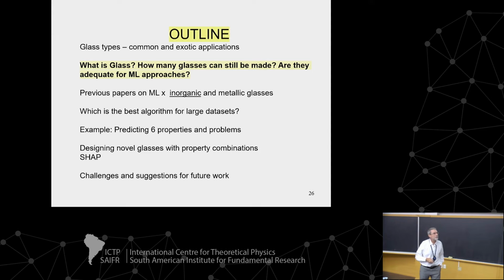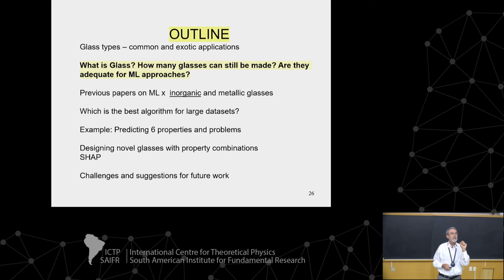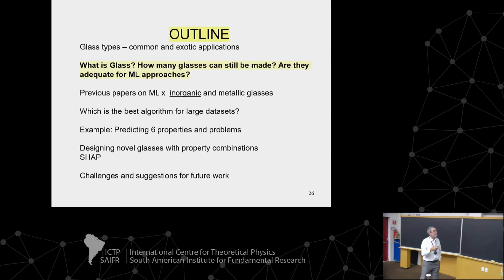But a glass that would plastify before breaking, there's no such thing then? No. Well, it shows plastic deformation at a very, very short scale. If you look at a nanometer scale, it has some plastic deformation in the range of 10 nanometers or so. So you can make an indentation in a glass with a diamond indentor. You have a flat glass, you press a diamond indentor, and look with an electron microscope, and you see some plastic flow on a scale of nanometers. Very short-range plastic flow, a little bit, not like a metal.